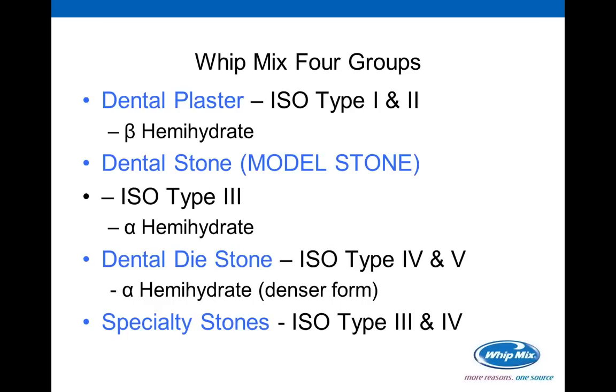The next group are the dental die stones. These are the ISO type 4 and 5 stones. This is also an alpha hemihydrate, but it is in a denser form, meaning that the crystal size of the particle size is smaller, and therefore they can be packed more densely. And we use them for generally creating master models. The last one are the specialty stones, and we'll talk a little further about some of those. Most of these are ISO type 3 and type 4 stones.